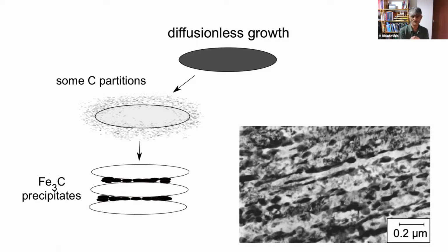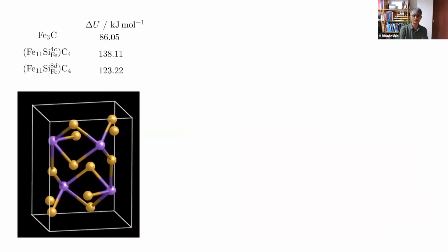Okay, so if you temper, then the silicon will escape, and you will be left with a negligible concentration inside the cementite, too small to make thermodynamic measurements. So even in principle, I can't get the thermodynamic data for silicon in cementite. So this is where first principles calculations come in.